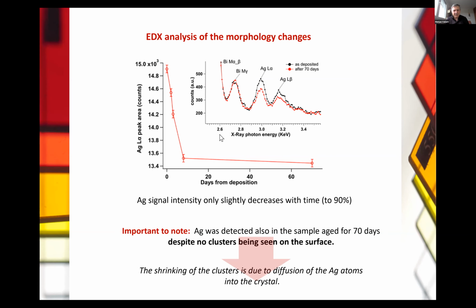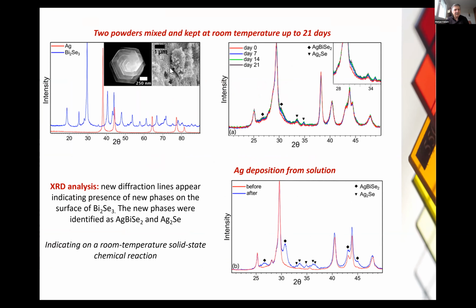So here we approach it a little bit differently. We produced nanoparticles of silver and nanoparticles of bismuth selenide, and we mixed them together, dried them, and just left them on the shelf for a number of days. And what we have seen is a slow increase of another phase. This is our XRD. So we see the appearance of some new diffraction lines.